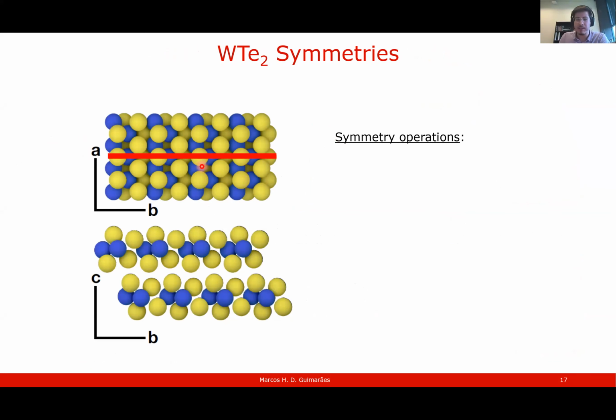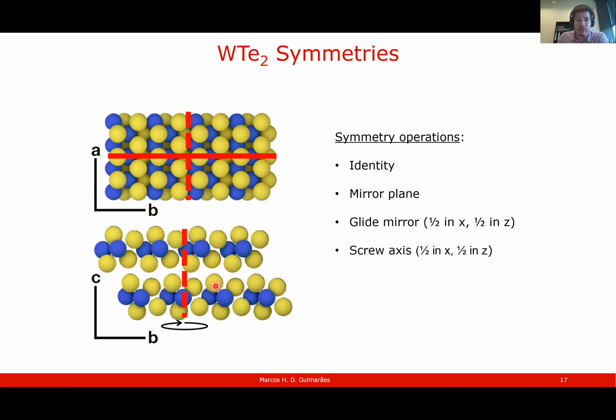So let's recap the symmetries of the crystal. Of course you have the identity, which leaves everything in place. You have a mirror plane along the b-axis of the crystal. You have a glide mirror, which is along the AC plane, plus a translation in the X and Z direction. And you have a screw axis, which is a C2 rotation and a translation in the X and Z direction. And this converts into a space group, for the people that like group theory, Pmn21.